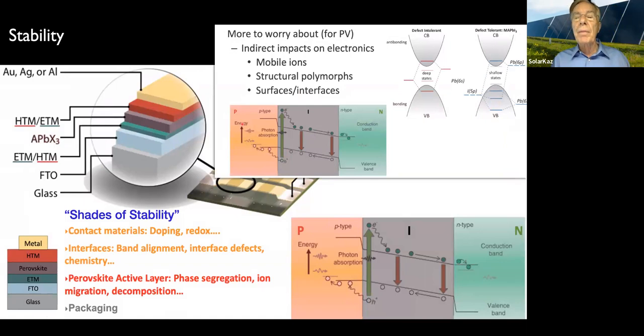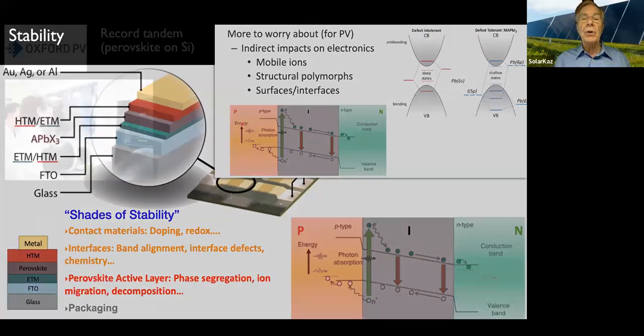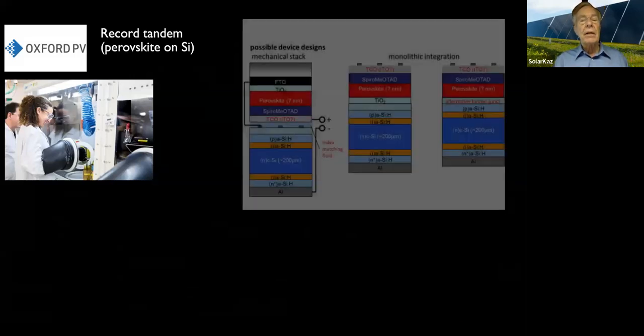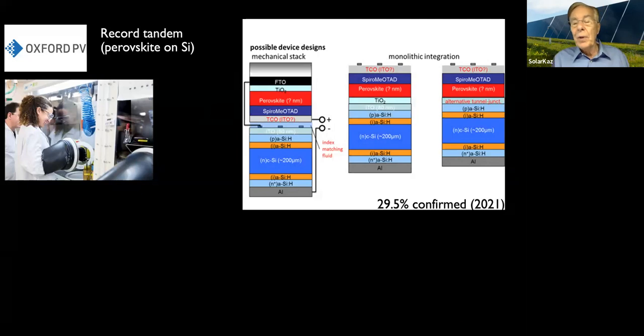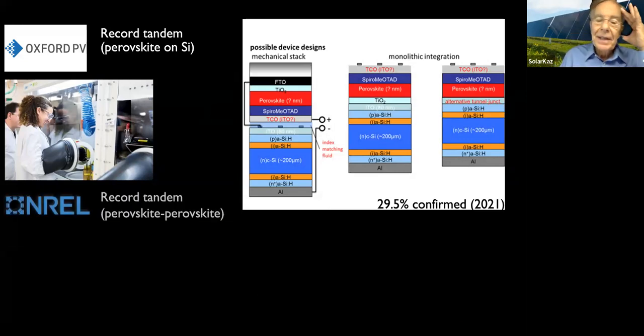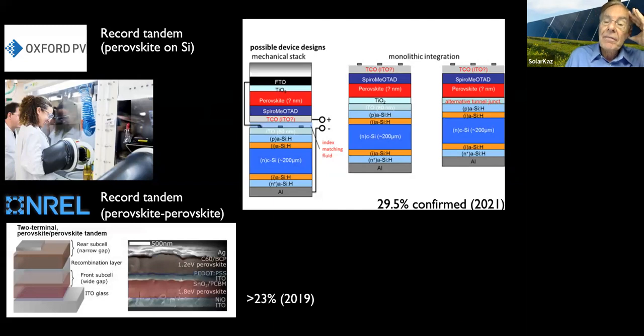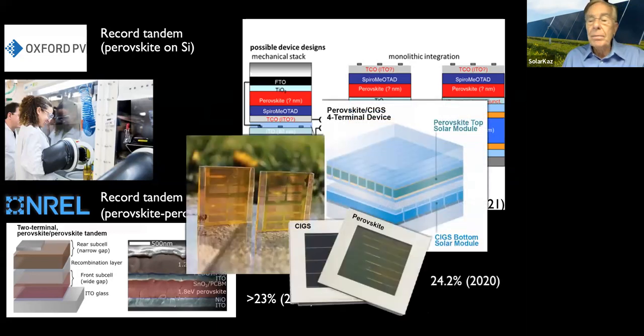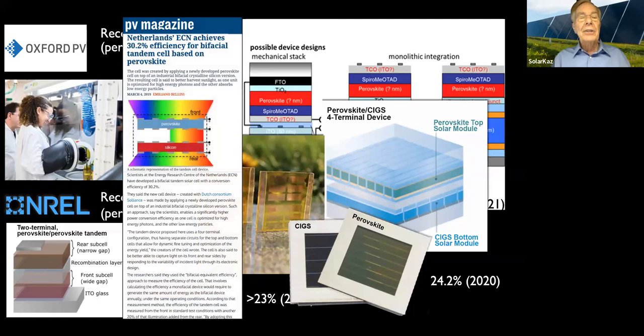It's more to worry about for other applications right now than it is for PV, but realize that these have not been solved yet. It's a great material with great demonstrations of efficiencies, but still a lot of work that we have to do about this to make it a large-scale commercial product. The records, okay, here are up at, as I said, 29.5% for a tandem, putting the perovskite on top of the silicon, shown here in this diagram. Even single perovskites, tandems have shown efficiencies above 23% on this. Oh, and perovskites with CIGS, okay, at above 24% in the tandem thing. So there's a lot of hope on this whole thing.